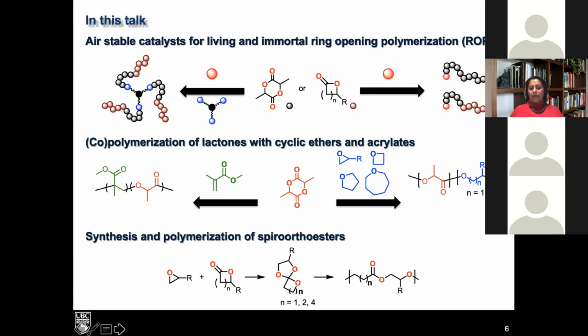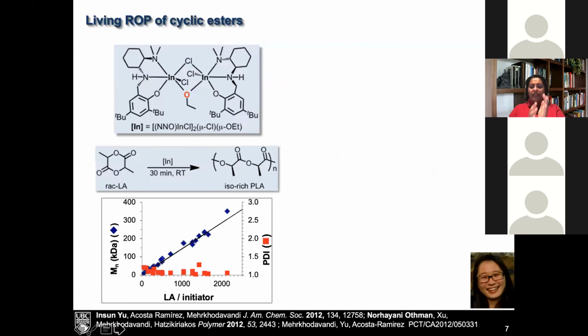And then finally, I'm going to show you a way to effectively block copolymerize epoxides and lactones by going through the spiro orthoester intermediates. If you choose the right catalyst system, we can form these 100% in situ and then ring open them effectively, forming an alternating copolymer with epoxides and lactide. So let's start with the first story. This is the first thing that we started working on in my group.